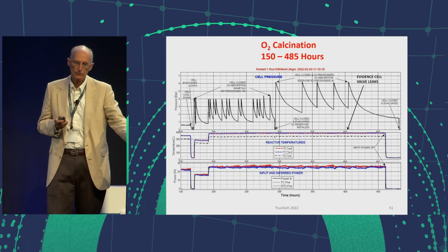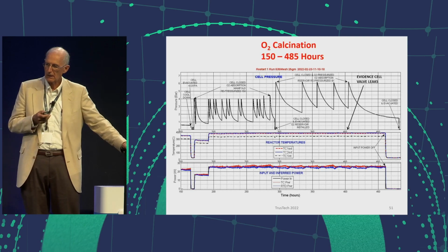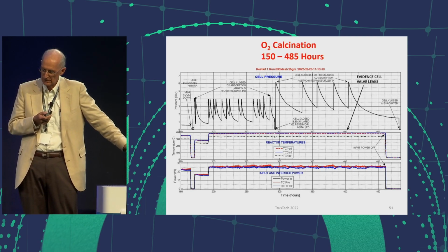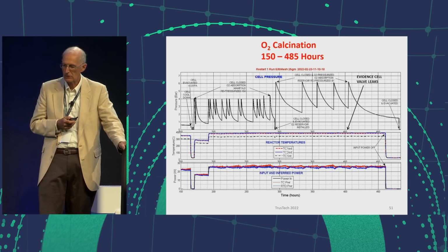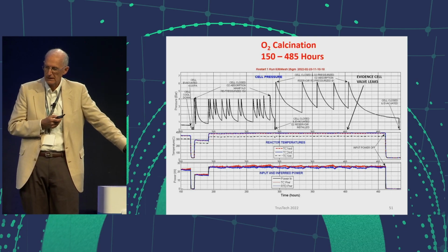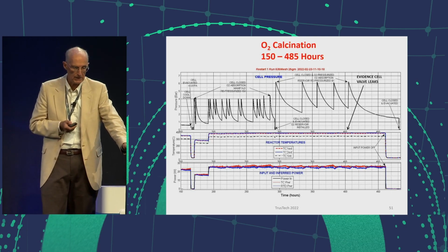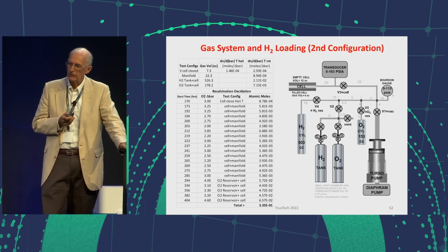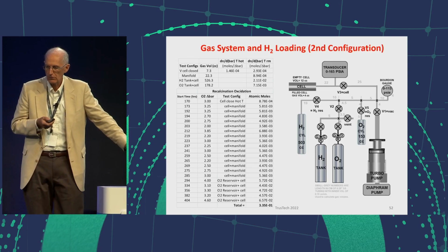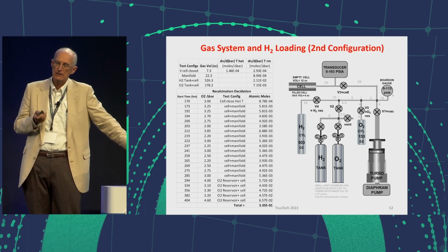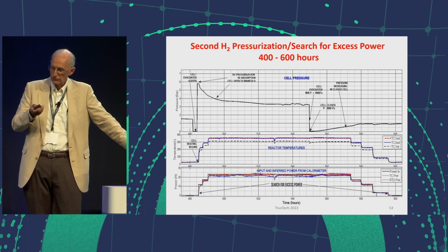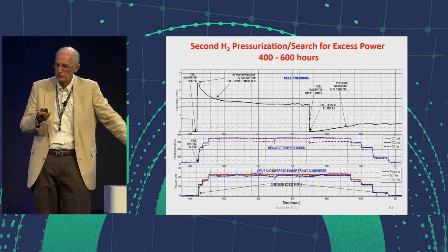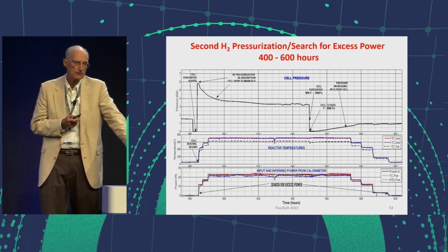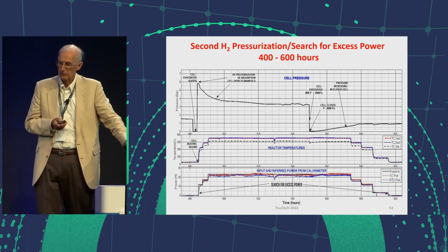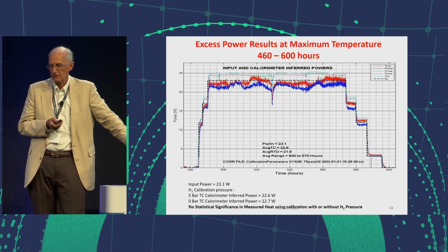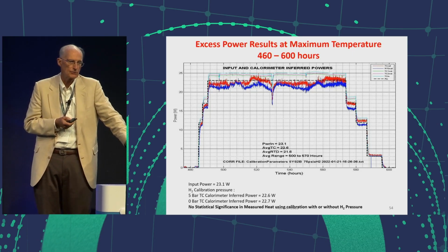After this was done, I then tried to do a second calcination by introducing oxygen. And each of those peaks you see in the top curve are the pressure and absorption of the oxygen. And you can see throughout the whole thing in the bottom curve that there was no excess heat during these measurements. This shows the modified gas system that I used for the oxygen and also a secondary introduction of hydrogen, which is shown in this slide here. And again, during this whole process, the bottom slide shows that basically there is zero excess heat measured by the calorimeters. This is a blow-up of that data, but basically it hugs zero within the accuracy of the calorimeter.